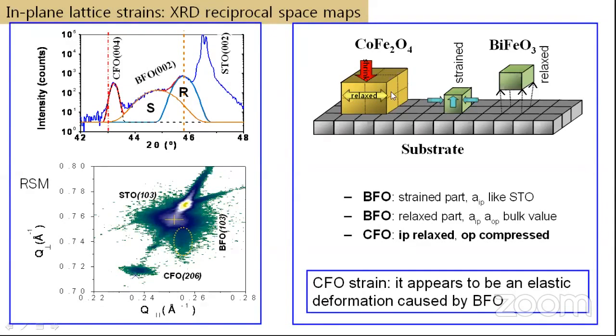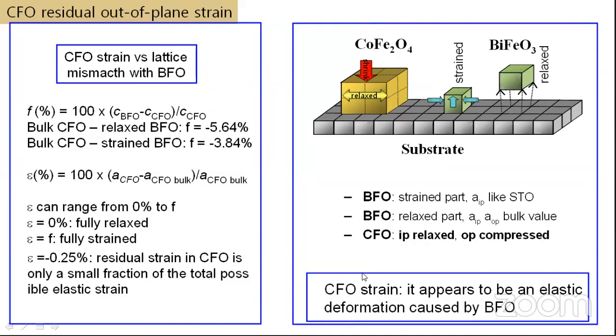Because of this interface between bismuth ferrite and cobalt ferrite, which are elastically coupled, the bismuth ferrite pulled the cobalt ferrite to accommodate itself here. So that's what is said here: the cobalt ferrite strain appears to be the elastic deformation caused by the bismuth ferrite. How this elastic coupling occurs, I don't want to get into the details.